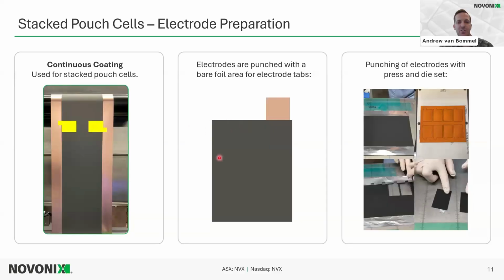So here's just a schematic of anode punch. So you'd have the copper to be able to weld on. When we finish coating and calendering, typically we sheet this material, in 200 by 200 millimeter sheets, and then we have a die set that's used to punch, in this case, 8 electrodes from one of those sheets. So here are 2 of those electrodes shown. So these are double-sided electrodes.